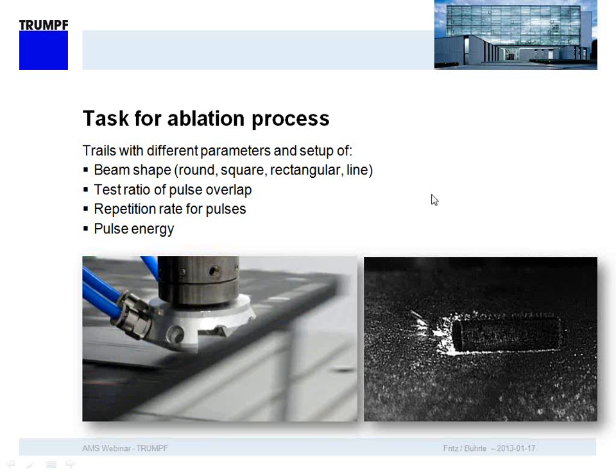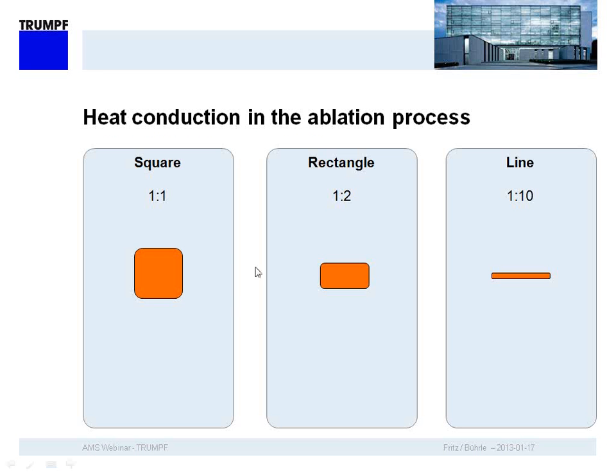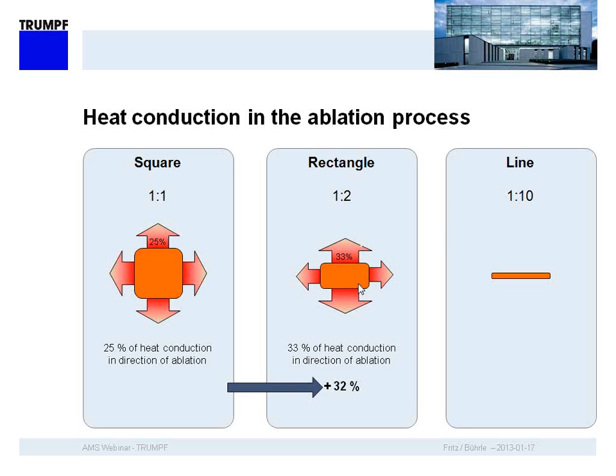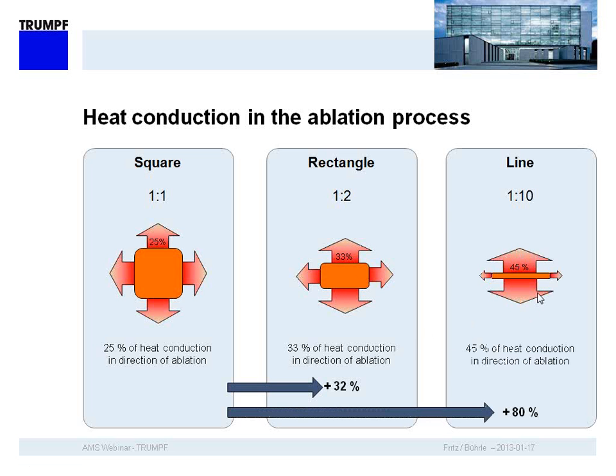So we did these different trials with these different beam shapes, like I explained, round, square, rectangular, and so on, and the different overlaps. What is very interesting is if we use a square spot, we go in that direction, for example, with the ablation, we can only use about 25% of the heat conduction for the ablation. That means the rest is just lost to the side edges of the spot. And we did the same with a rectangle spot and with a line spot. And it was very interesting to see that we had a very high possibility and power to go in that direction. But what we do, we use the same energy, but on a smaller surface.